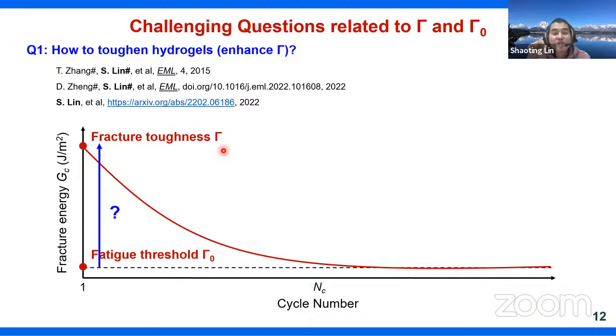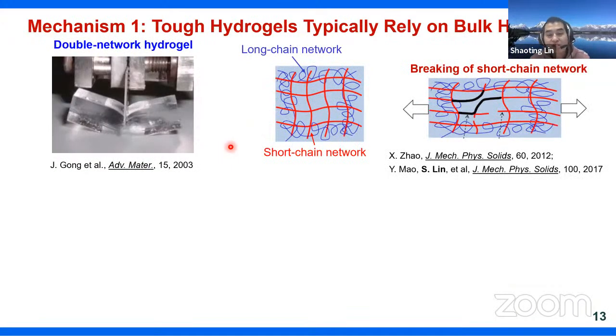Okay. So the first mechanism dates back to Jianping Gong's double network hydrogel, which requires introduction of a giant hysteresis. The double network hydrogel contains two networks. One is a long chain polymer network. The other one is a short chain polymer network. When the material is deformed, the long chain network is floppy. They can highly deform, but they remain intact, with no damage. Okay. However, the short chain network is relatively stiff. They are inextensible, so they experience so-called progressive damage.